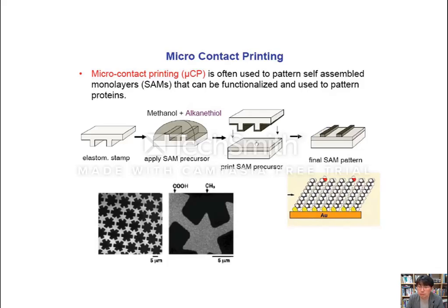That's the problem. So that's why the substrate is treated with a precursor that has strong adhesion to the material coated on the mold. Then they hold that material, rather than the material moving back with the mold. So that's the mechanism. Micro contact printing became popular because its productivity is really good, like stamping, right? So that's another method you can use to build microstructures, micro contact printing.